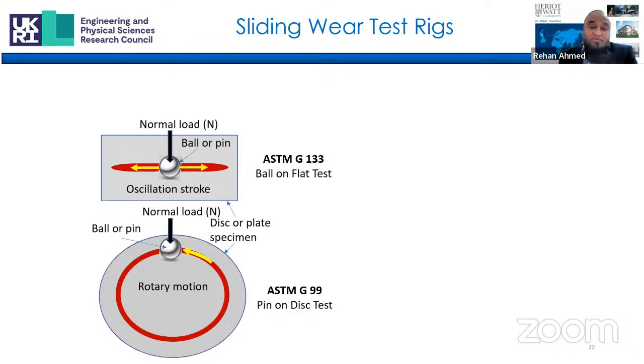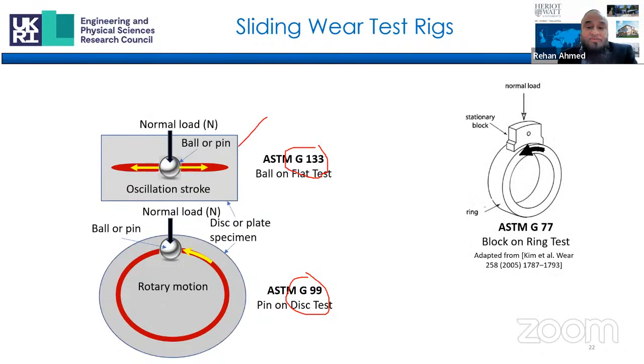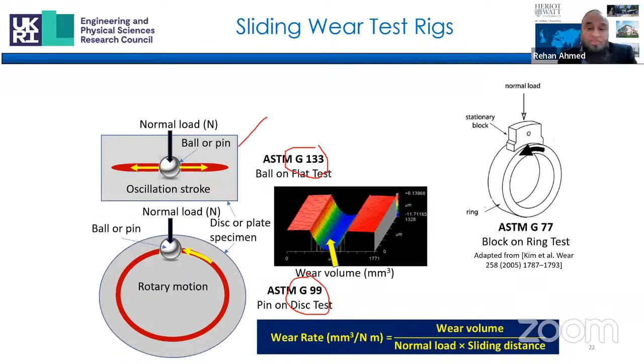So in ASTM G133 and G99, the normal load is applied to the ball or the pin, and the difference between them lies in the sliding direction, which is reciprocating in G133 and rotary in G99. Another configuration is the ASTM G77 block on ring test, as shown over here. Now, in all of these tests, we measure the wear volume using the wear scar and use the information about the normal load and the total sliding distance to evaluate the wear rate. And the post-test evaluations of these wear tracks can help us identify the wear mechanisms. And a number of factors are important here, as discussed in the next slide.